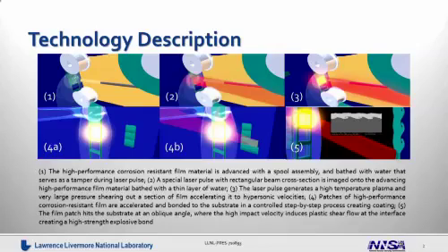As shown in frames 4A and 4B, the plasma creates a very intense pressure pulse, which shears out a rectangular slab of film material. This film material is then accelerated at an oblique angle, striking the substrate at hypersonic velocity, as shown in frame 5. By striking the interface between the film and the substrate at an oblique angle at very high velocity, we have shear plastic flow. The shear plastic flow forms a highly localized, explosively bonded interface. By performing the HVLAD process, we're capable of producing the strongest interfacial bond strength of any known coating process.